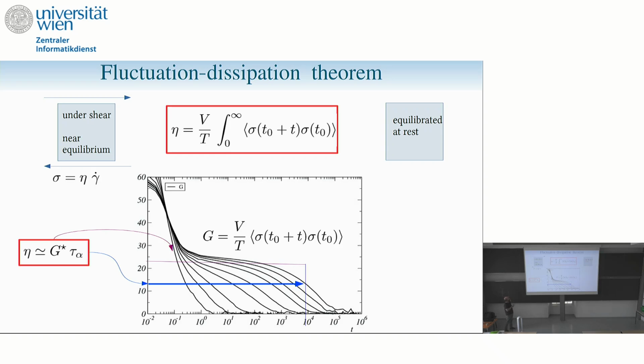So here you're looking at a sheared liquid, where you define viscosity as the ratio between stress and strain rate. You could also consider a liquid at rest, look at the stress as a function of time, and look at the autocorrelation of stress. The integral below the autocorrelation of stress gives you the viscosity. If you take a liquid at high temperature, the autocorrelation of stress drops like that. If you cool down, you start to see a shoulder developing, and if you cool down much more, a shoulder extending much farther. Here you see a plateau developing, which corresponds to the elastic behavior of the liquid, and then a relaxation. Again, the integral below that curve is the viscosity.